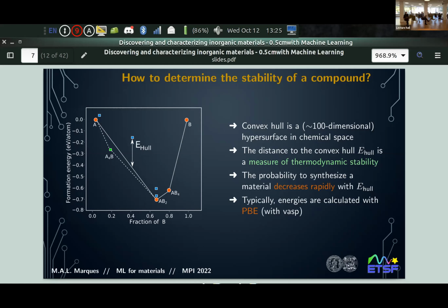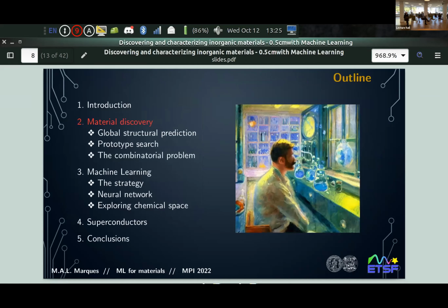So keep this order of magnitude in mind. 50, 100 meV per atom, there is a good chance that you can synthesize things. More than that, the probability decreases exponentially. Okay, as simple as that. The scale here, you see, it's 700 meV. You will see that the scale is actually larger than that. I will show you that. Typically, we calculate our energies with density functional theory in perfectly standard ways. We can discuss the errors afterwards if you want. I don't think this is important.